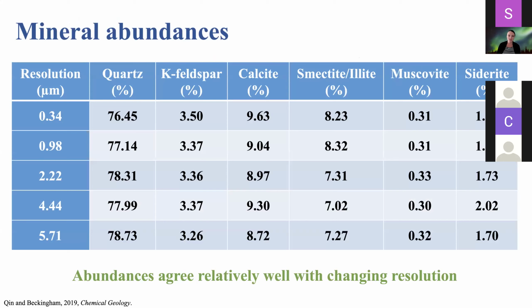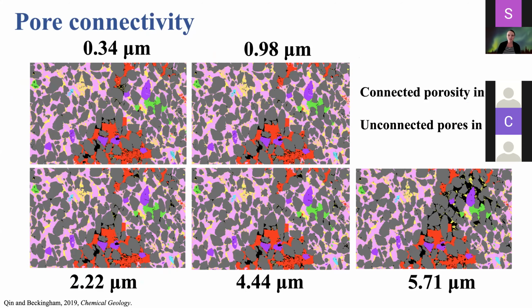In terms of abundances or volume fractions, what we found is that there was really little variation in the volume fractions with changing image resolution. We then wanted to understand where the fluid would flow, so we quantified the pore connectivity. So you can see connected porosity in pink and unconnected pores in black.